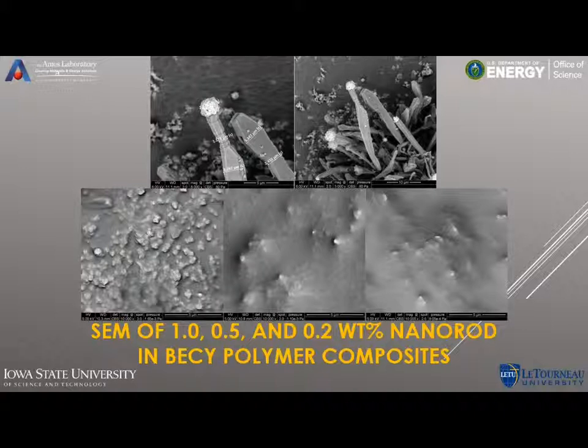We just looked at the nanotubes themselves one day with the scanning electron microscope and found these nanorods in there. And so these are aluminum nitride, and you can see they have growth rings on them. And if you look carefully, that's sort of hexagonal shape because the aluminum nitride itself takes on a hexagonal morphology.